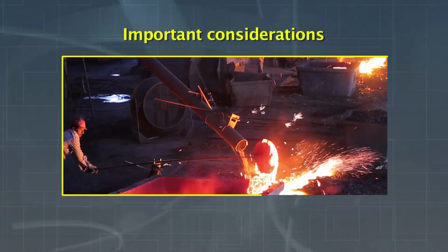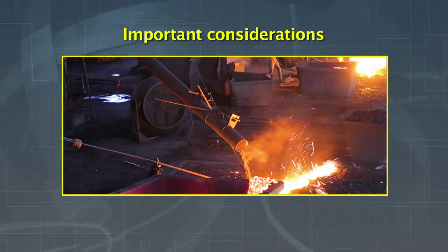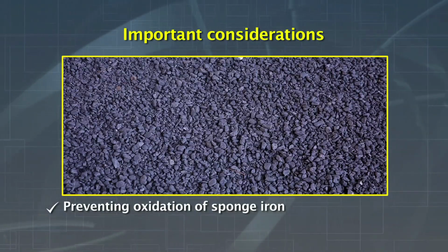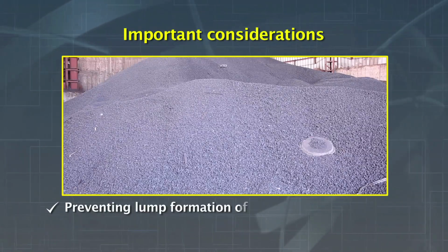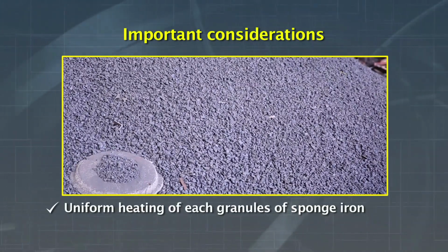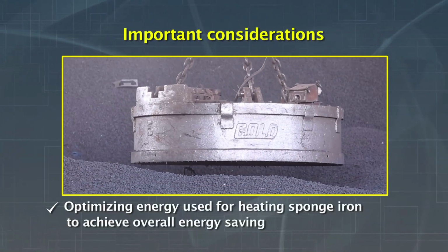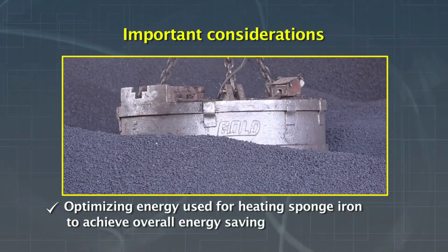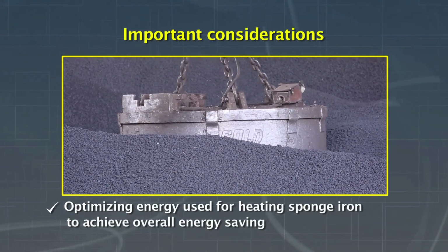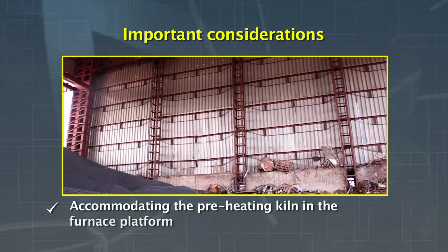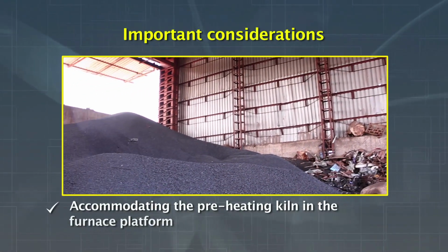Some of the important considerations for the system to operate are: preventing oxidation of sponge iron, preventing lump formation of sponge iron, uniform heating of each granule of sponge iron, optimizing energy used for heating sponge iron to achieve overall energy saving, and accommodating the preheating kiln in the furnace platform.